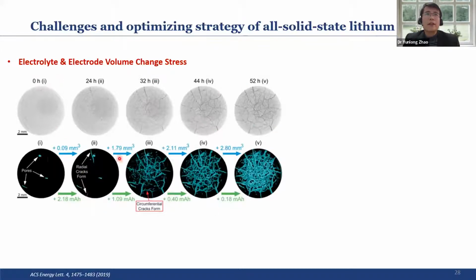So you can see there are a lot of cracks inside, and with a lot of cracks, the performance, especially the ionic conductivity, will dramatically decrease. This is maybe because of dendrite growth, or the anode or cathode electrode materials' volume changes, which can create some pressure and then lead to this kind of crack.